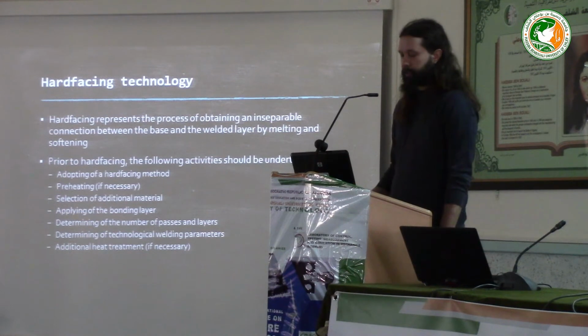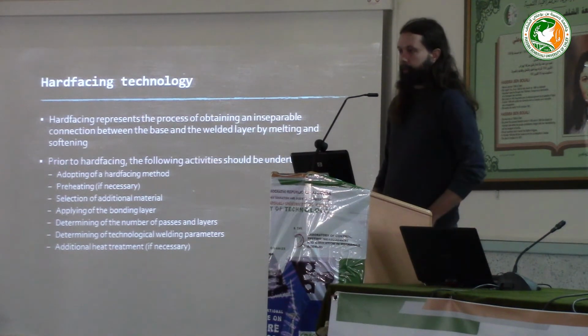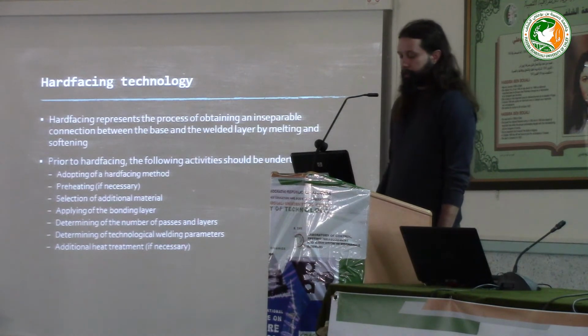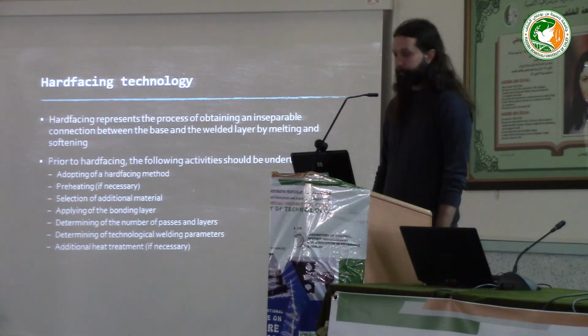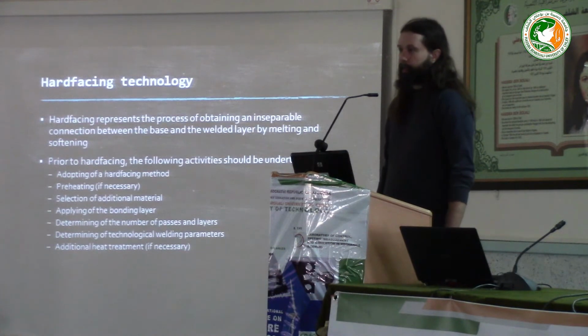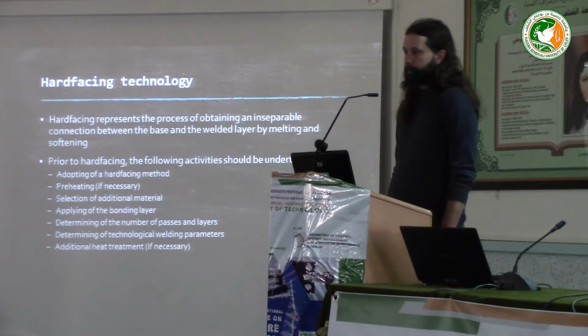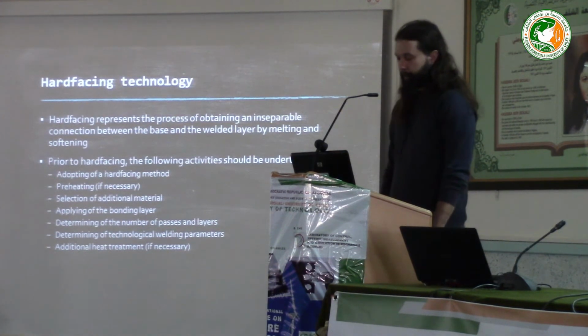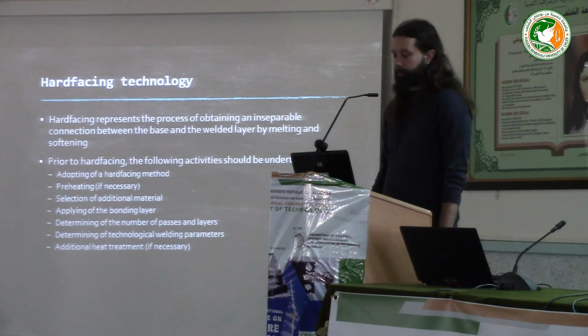First of all, as we mentioned, the method for hard facing needs to be carefully selected. Then, if there is necessity, preheating should be performed. Next, we select the additional material and apply the bonding layer. Following this step is the determining of the number of passes and layers for the welding and the determining of technological welding parameters such as amperage, welding speed, and angle. In case there is need, additional heat treatment is performed as well.